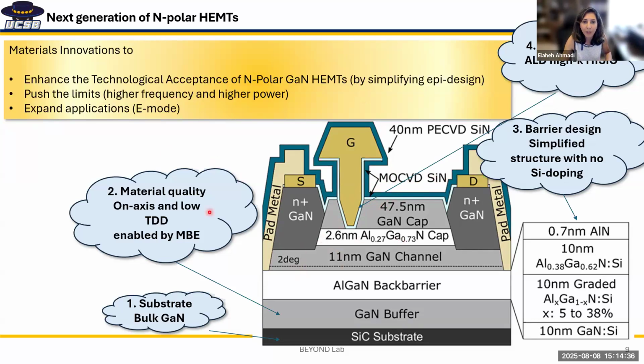So my goal has been to see if we can simplify the epi design. The other thing was to push the limits, go to higher frequencies, higher power, and also expand applications and see if we can do E-mode devices with nitrogen polar using new dielectrics. For this, there are four main things that we have focused on. First of all, we are using bulk GaN with low dislocation on axis. We don't need miscut by MBE. Our group is focused on MBE growth, and so we don't need the miscut. We use bulk GaN substrate, low dislocation.